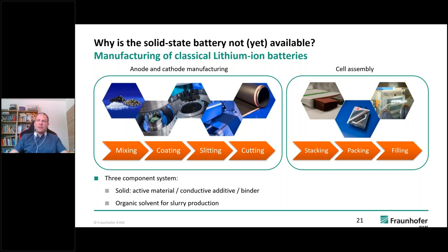Then they are packed, in this case, in a so-called pouch bag, as it's an aluminum polymer material, which is actually closing the cell. And in the last step, we are just filling in, into the separator which is laid in between, the white one here, the electrolyte. And the thing is, up to this point, everything is stable in air. We can use this everywhere, build it easily in a plant, and don't have to take too much caution, other than for the organic solvent that is used for the paste production. When we get to the filling step, then we get to a point where it's air sensitive, meaning that in our case, it's in a glove box under argon, where we can fill in the electrolyte, because we don't want water inside of the cell in the end,